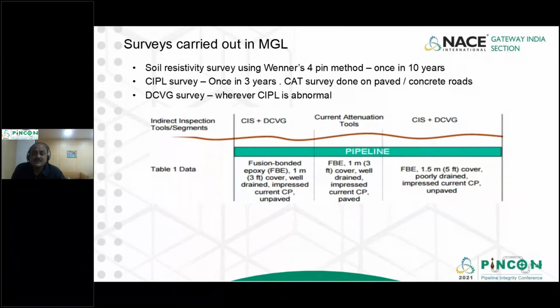Now, the surveys which we have carried out: we do a soil resistivity survey using the 4-pin method once in 10 years. CIPL survey we do once in 3 years, and CAT survey on paved and concrete roads. DCVG survey is done wherever we find CIPL readings abnormal. So we figure out where we have coating damages, and we rectify them depending upon the IR values which we have taken. So this is the data, CIPS plus DCVG for fusion bonded epoxy.